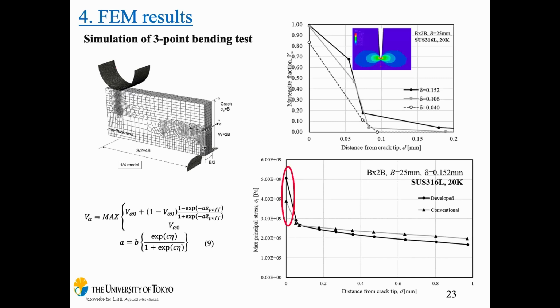And the bottom right graph shows the maximum principal stress near the crack tip. To compare the value at the crack tip, compared with the conventional FEM, the value in the developed FEM is higher. So it suggests that the conventional FEM does not consider the TRIP, and as a result, the stress may be underestimated.